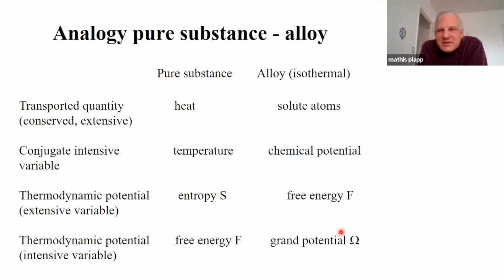So you can deduce this in some sense from a little table that gives the analogies between a pure substance and an alloy. You know that in both cases, I have a transport phenomenon. In the pure substance, it's heat. In the alloy, it's solute. There's a thermodynamically conjugate, intensive variable, which is the temperature for the pure substance. It's the chemical potential for the alloy. Now, if you continue this table, you see that you can always have several thermodynamic potentials that are all equivalent, but they are different whether you express them in the extensive or in the intensive variable. So for a pure substance, if you want to use the energy, which is the extensive variable, the heat, then your potential is the entropy. If you want to use temperature, then it's the free energy.